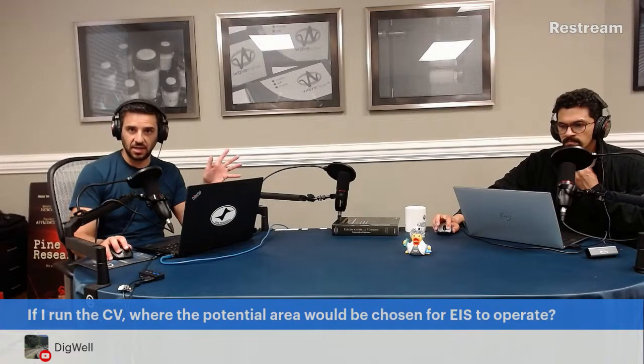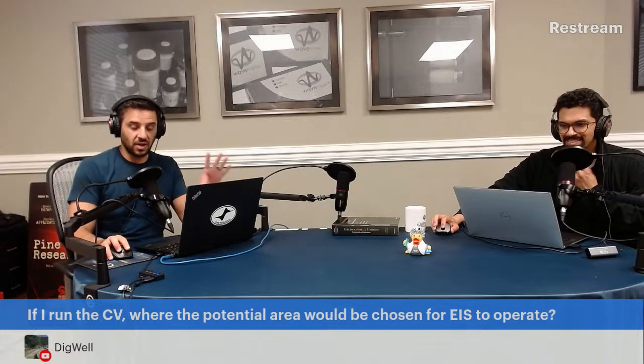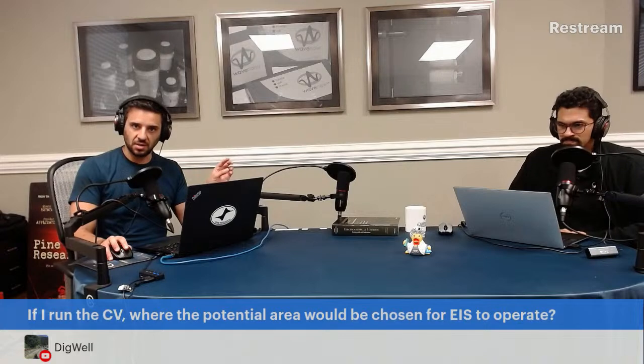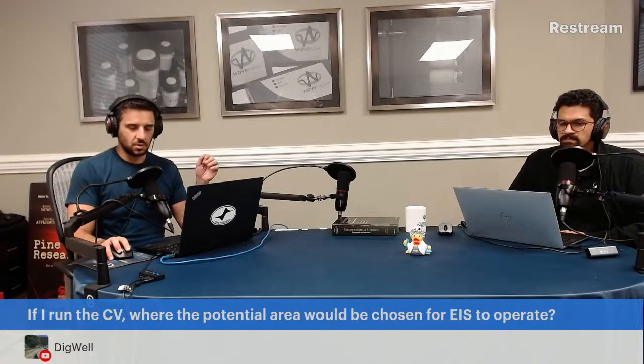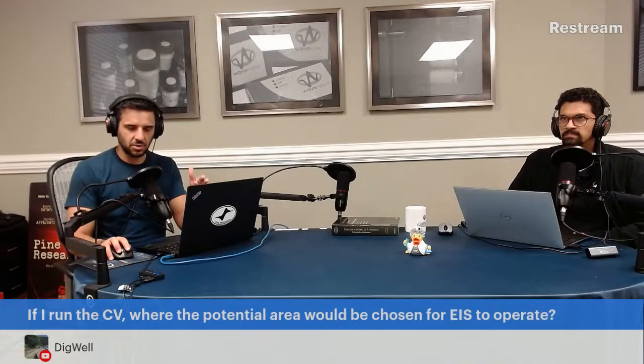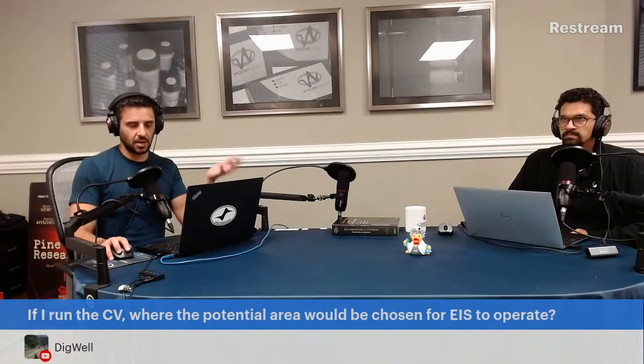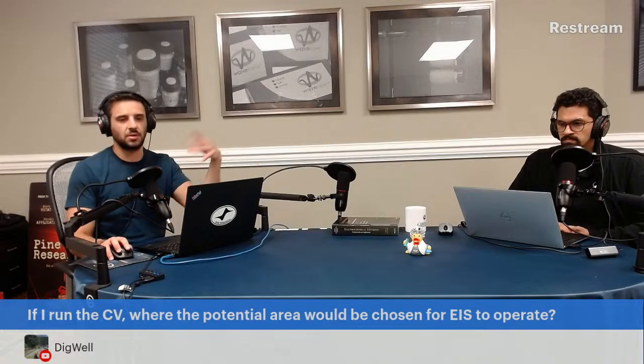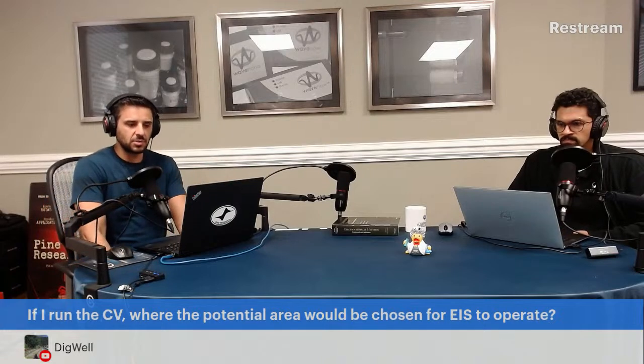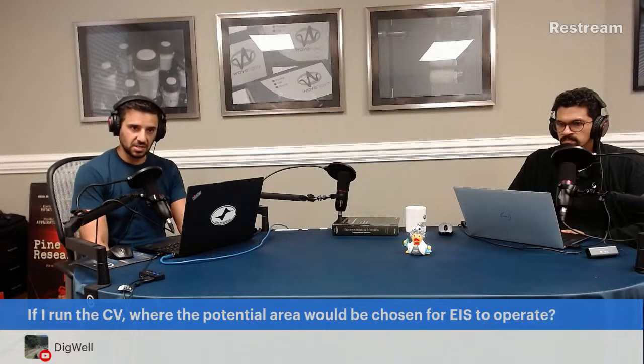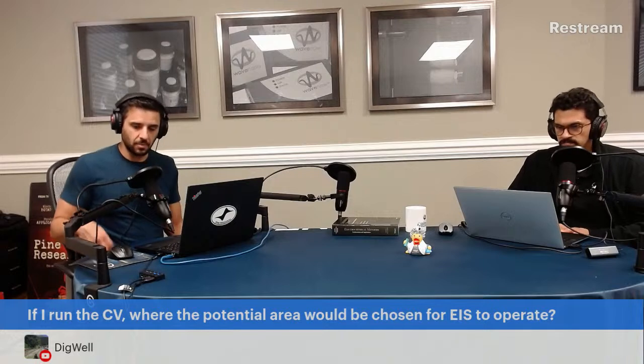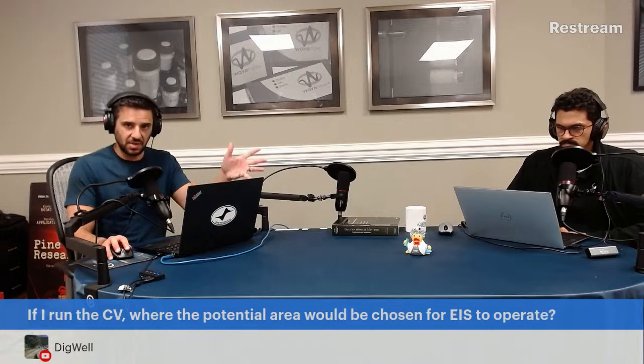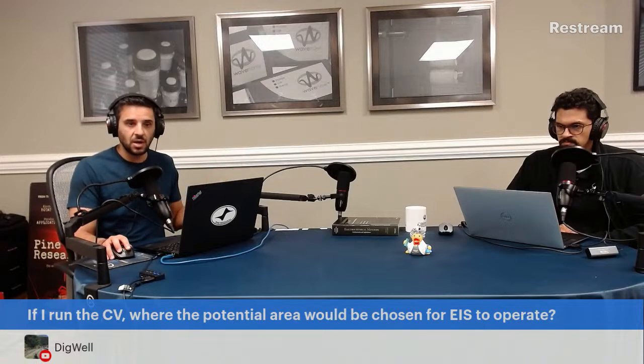It's never going to be this way exactly because nothing works ideally. However, in theory, the solution resistance should be the same regardless of where you are along the state of charge curve. So if you perform it at open circuit potential or you're halfway through charging or discharging, for the most part, the electrolyte can change. The SEI can decompose it a little. There are some situations where what I'm saying isn't exactly correct, but for the most part, the electrolyte is largely unchanged. The solution resistance is, in theory, largely unchanged throughout the course of an experiment, even over repetitive cycles. While experimentally you'll measure some small changes, for the most part, it doesn't matter where along the curve you are. So your best bet is just to do it at OCP, at OCV, whatever your open circuit potential voltage is.